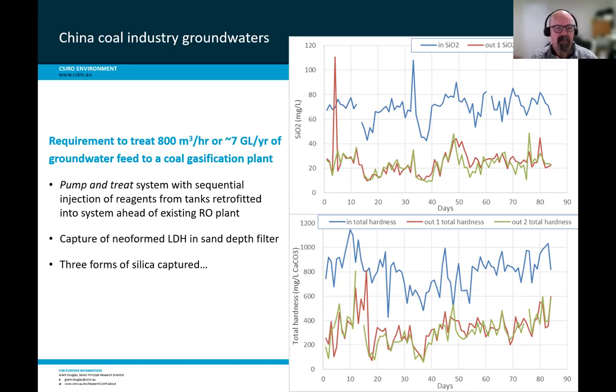On the right-hand side, in the top image, we've got the silica in blue and 2 streams of silica out of the system. You can see the silica in was anywhere between 60 and 80 milligrams per litre. The silica out was probably around 20 milligrams per litre. If you look at the total hardness, that's quite variable, but let's just say it's anywhere between 600 and 1,000 coming in. Over time in the outlets, it's probably around 200, and it rose over time as the inlet concentration did, to say 400 or 500 milligrams per litre.